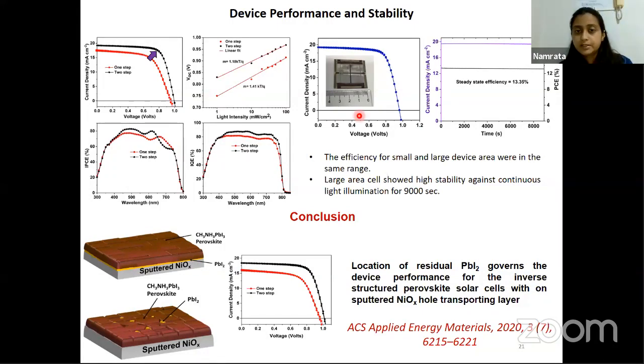So next, the active area for these devices was quite small, 0.185 centimeters square. So the next target was to make a bigger cell with active area of 1 centimeter square. And here in this figure, we have a device with active area of 1 centimeter square. And very surprisingly, we could achieve almost the same efficiency with the two-step method